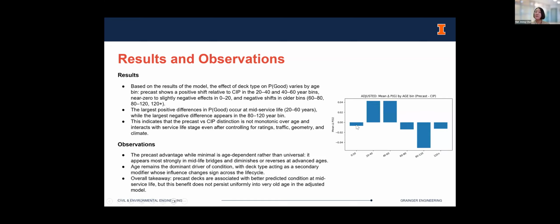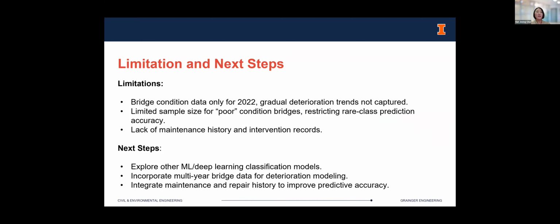As you see here, it varies. Depending upon those ages, we have found that this relative performance of precast bridges varies. For the middle ages, 20 to 40 years, precast concrete bridges seem to be performing slightly better than the CIP bridges, but for the other age bins, we didn't find this specific behavior. So this advantage of using precast concrete may vary depending upon the life stage of these bridges. And regarding the limitations of our research, we have used only 2022 year data, and we haven't considered other data. So we are planning to expand our data set to a longitudinal data set.